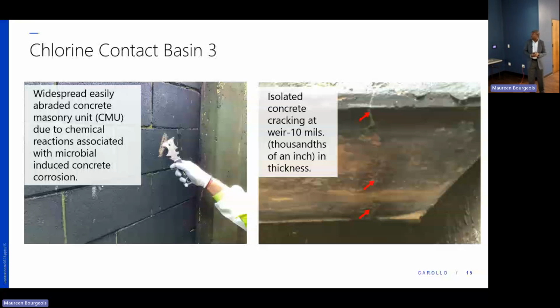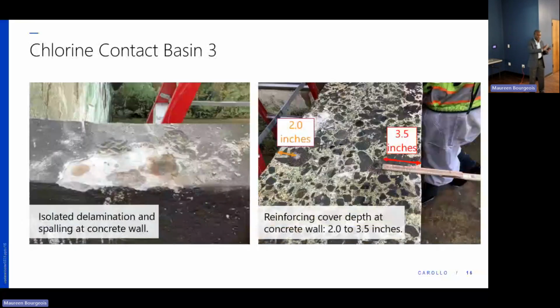Then additionally, on one end also, we saw isolated delamination or spalling of the concrete wall. Delamination is usually when the concrete, for example, is not well bonded, and so it begins to spall off or come off. And the spalling may also be a piece of the concrete coming off. It could just have been some mechanical impact, maybe somebody hit it, or perhaps the concrete at that point was probably deteriorated by some other means. So we captured that as well, an isolated incident.